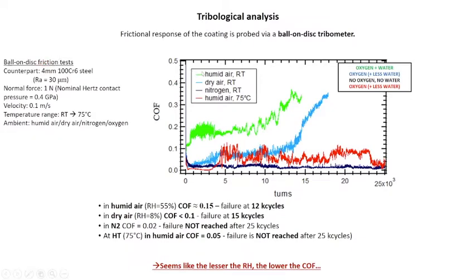The tests have been performed in 3 different conditions. So humid air, room temperature, the green line; dry air, room temperature, which means absence of humidity but presence of oxygen, which is this light blue; and in absence of humidity and absence of oxygen, so in nitrogen atmosphere at room temperature. And finally, in humid atmosphere, but at a slightly higher temperature with respect to room temperature.